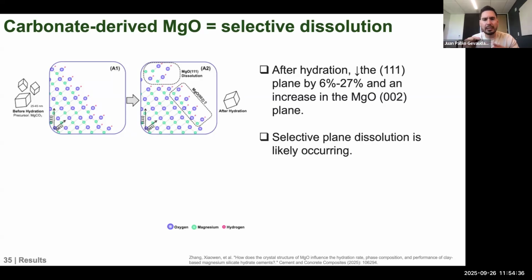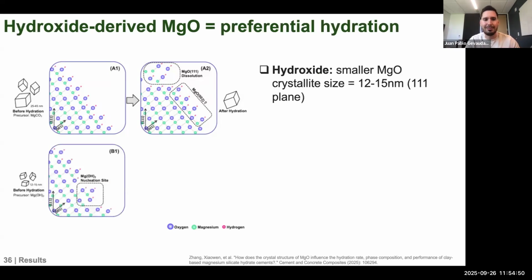But what is fascinating here is that there seems to be this selective plane dissolution that is likely occurring in carbonate-derived magnesium oxide. Now, is this the same for brucite? No, it's not. Well, it's important to understand that brucite has these nucleation sites, and it has a smaller crystallite size for that 111 plane of the magnesium oxide produced.